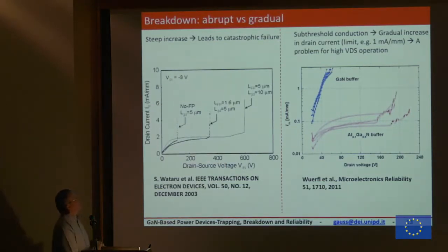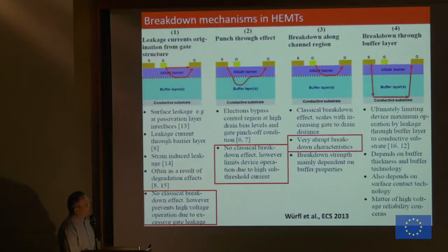Then we may see a kind of hard breakdown or smooth breakdown, but there is a nice paper from Joachim Wuerfl, presented at ECS 2013, that really looks at different breakdown mechanisms. And here you see what Farid spoke about yesterday. This is for very high voltages. This is your limitation. The breakdown goes this way, to the conductive substrate if this is silicon, and goes up. So this is the conduction path. If you want to increase the breakdown, you have to increase the thickness of this layer. Then we may have a breakdown in the channel, but for this you really need the avalanche. This is not very often seen.